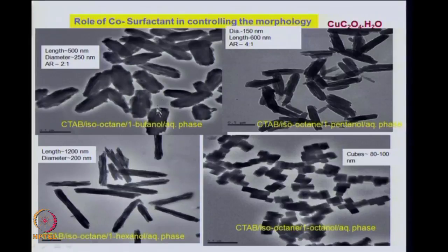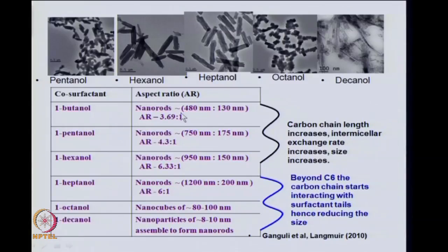So, if you go from butanol to pentanol to hexanol, you see the aspect ratio is changing, and then beyond hexanol the aspect ratio comes back, it becomes cubes. So, there is an optimal chain length of the co-surfactant, and it appears that 6 carbon is the optimal size. We have seen that if you increase beyond hexanol, the aspect ratio starts to become less, and in octanol and decanol, which are very large chain co-surfactants, 8 carbon and 10 carbon, they become more uniform and nanocubes and nanoparticles start forming.